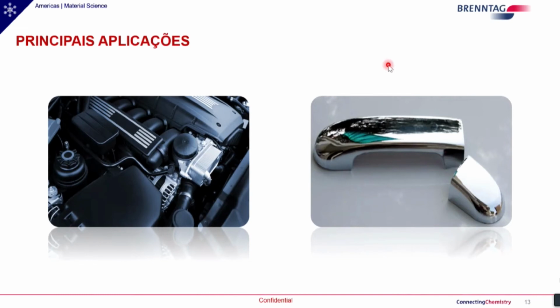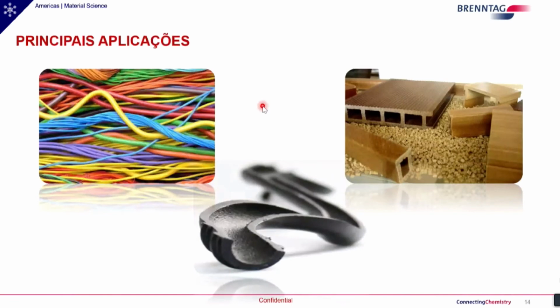Polypropylene has to go through a couple of processes, such as what we call the corona process. It's like a shock of electrons in the surface so that the paint adheres to the part. And with the compatibilizing agent, you don't need these processes anymore, because it changes the polarity of the polypropylene to create this better interaction with the paint, with the metallic paint.